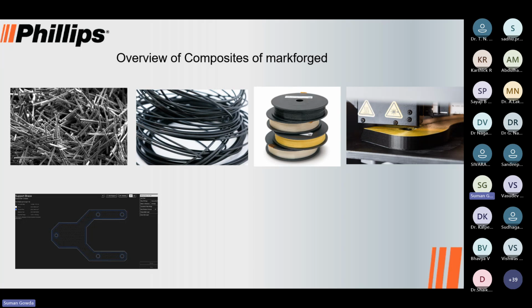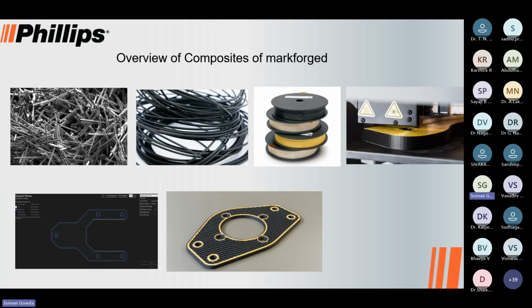I can even increase the strength by increasing the fiber lines so that the strength becomes more superior based on my requirement. The advantage I get over this is that the strength to weight ratio is completely under our control. We don't have to depend upon just the density of the part. So I can go even more lightweight and still achieve the same strength that is required for my end use. So here are the components as they would look once we deposit the material.